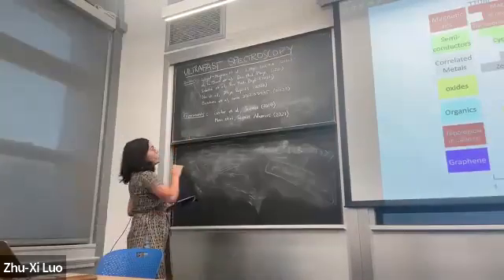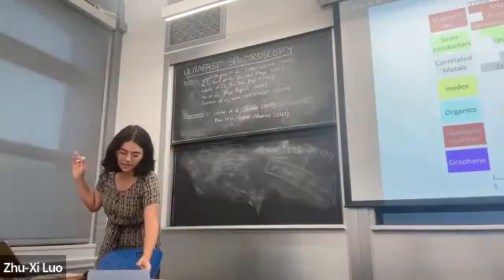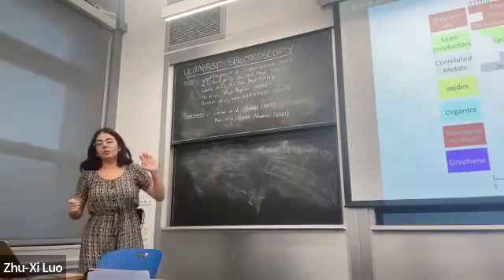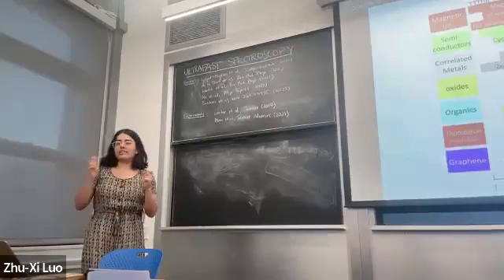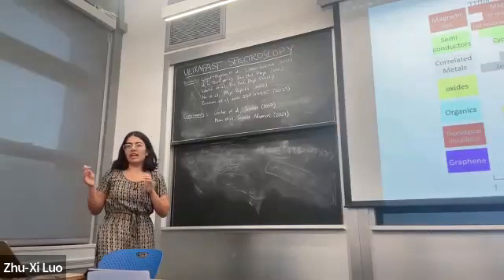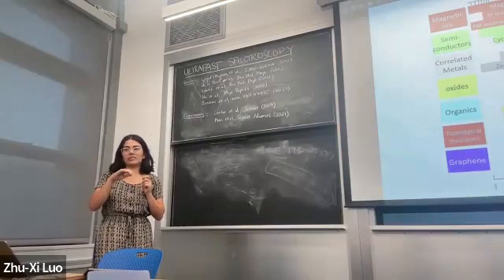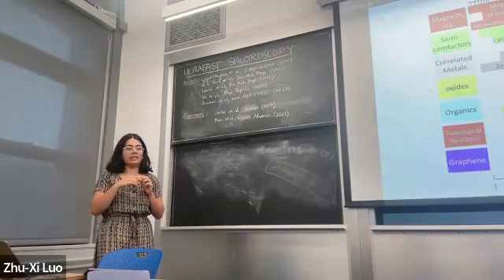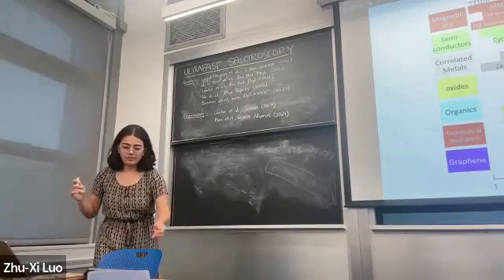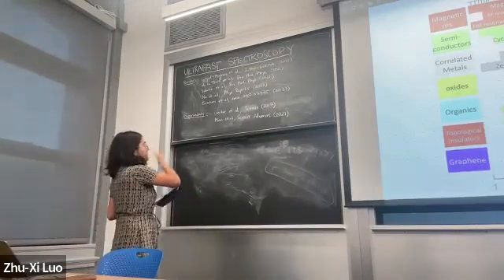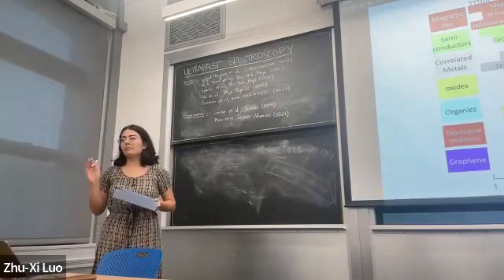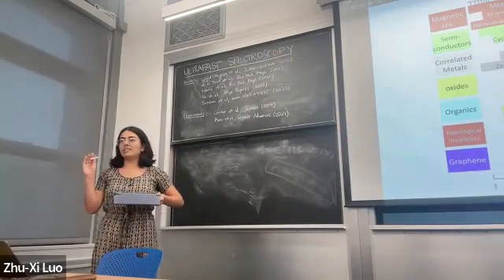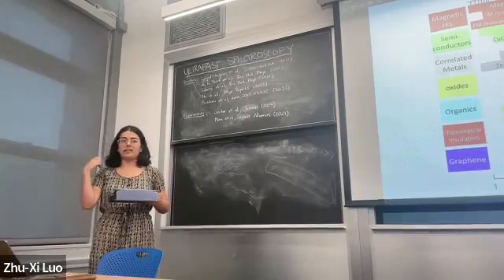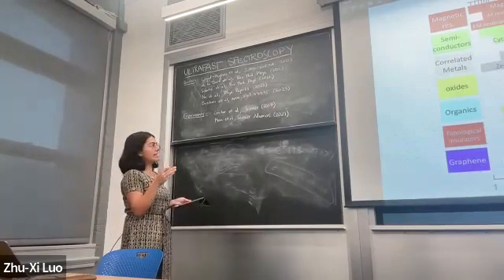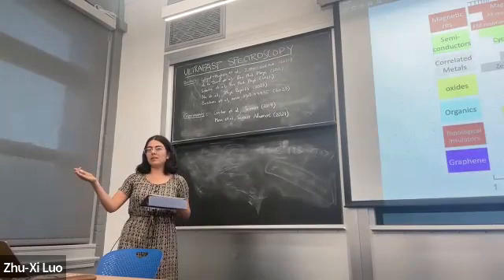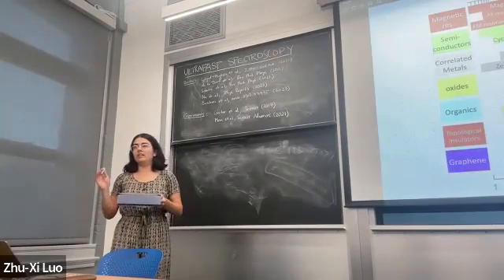And then I will definitely talk about this first paper where they use time-resolved ARPES and time-resolved X-ray diffraction techniques to directly measure the electron-phonon coupling in an iron-based superconductor. And if time permits, I will also talk about the second paper looking at excitons in monolayer TMDs, where they, again, use these time-resolved ARPES techniques to directly image the exciton wave function.